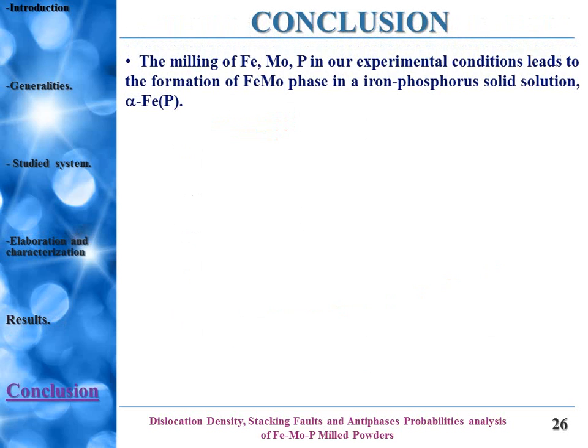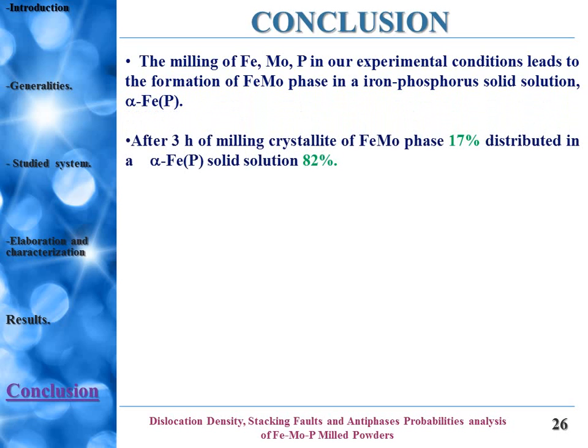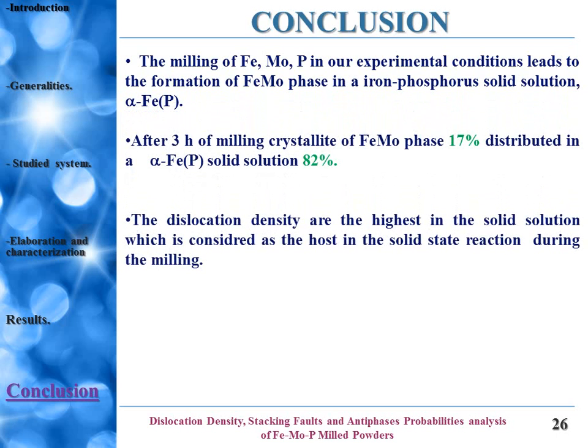Conclusion: the milling of iron molybdenum phosphor in our experimental conditions leads to the formation of iron molybdenum phase in the iron phosphorus solid solution. After 3 hours of milling, crystallites of iron molybdenum phase are 17%, distributed in alpha iron phosphorus solid solution, 82%.